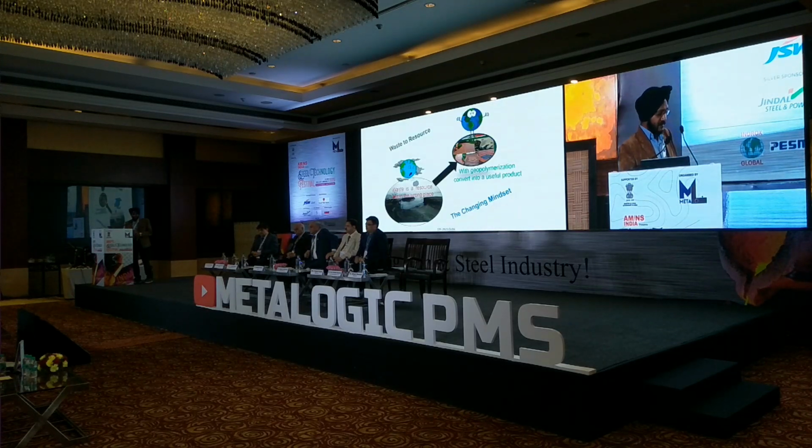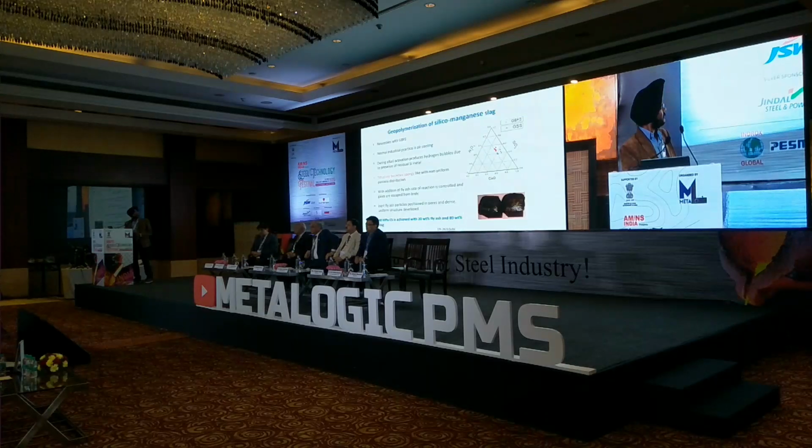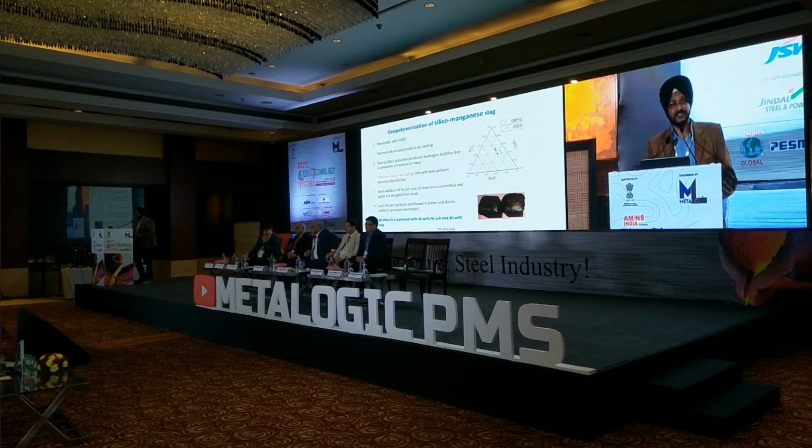So we used the geopolymerization technique for the application of silicomanganese slag, as it resembles the granulated blast furnace slag, and only differs due to the content of MnO. The normal practice in industry is air cooling of this slag, but we modified this slag by water quenching, water granulation, and we mixed it with fly ash and also alkali to form spongy structures, and we have got 40 megapascal of compressive strength with 28% fly ash and 72% silicomanganese slag, which is comparable to the compressive strength obtained with the granulated blast furnace slag.